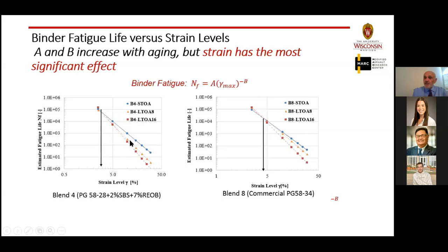And what really struck me after I studied the IFIT test, you observe a very similar phenomenon. As you age, you see the post-peak slope get increasing significantly. And in fact, I'll show you the relationship between these two slopes. So it is very clear to me that without measuring the behavior at multiple strain levels, including the large strains, we could be missing a lot of the important properties of binders or mixtures.